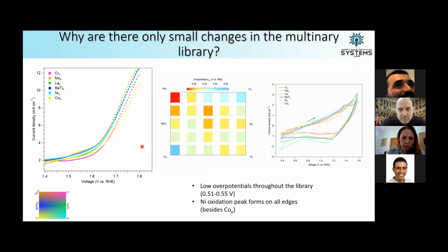And indeed, if you look at the map of 25 points that we scanned all over the library, the overpotential really doesn't change dramatically throughout the library. Yeah, it changes maybe from the cobalt to the molybdenum edge or from the molybdenum to the chromium edge, but the changes are only around 40 millivolts, which is quite small. So we expected much larger changes.